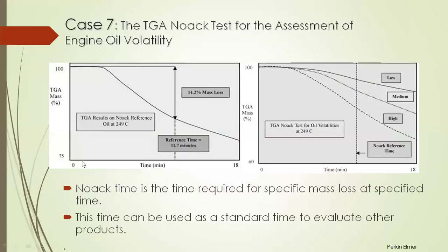What these people do, they do an isothermal TGA of the sample and find out the weight loss at a particular time. This is suppose your benchmark. Then you get oil from different suppliers. You do a similar type of experiment. The experimental condition should be the same; you should not change the experimental condition. And you do a similar type of TGA curve. And at a particular time of your interest, you find out what weight loss these materials are giving. And you can then choose which oil to use and which oil to discard. So you see, TGA you can use in quality control, choosing your material